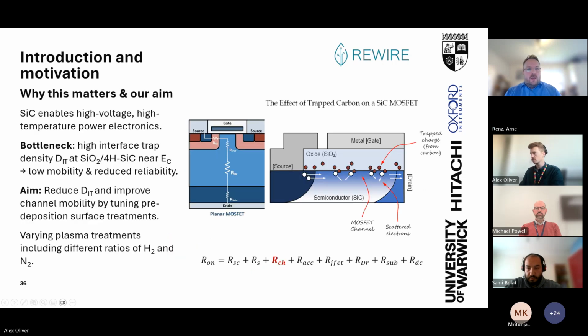So now we've talked a lot about the bottleneck, and in this project that we worked on, our aim was to reduce this and improve the channel mobility. And we did this by fundamentally changing the technology. We moved away from thermal oxidation and went to a process that uses pure chemistry, basically. You have a silicon precursor, you have an oxygen precursor, they react and they come down on the surface. You do not consume anything of the underlying semiconductor material.